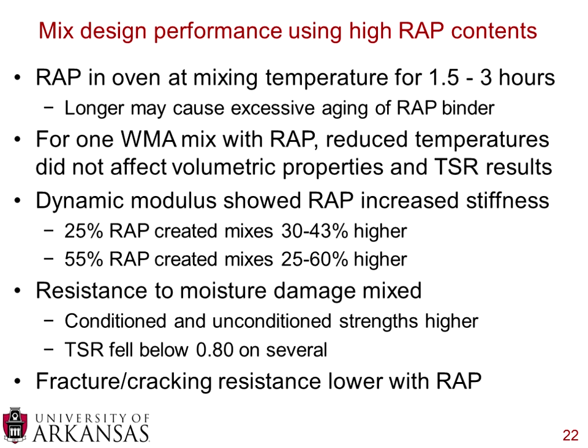They found that one of the tricky things about the moisture damage test, the tensile strength ratio, is that you take your unconditioned sample, which is just a normal asphalt concrete sample that you make in the lab, and you compare that to what's called a conditioned sample, a moisture conditioned sample. For the moisture conditioned sample, what you do is you take your asphalt concrete sample, place it in a bath, place it in a vacuum, and you suck water into that mix to where there's anywhere between, I believe it's 55 and 70% moisture within that mix. Then you run a test on that moisture conditioned sample. So you have both conditioned and unconditioned tensile strengths. The TSR, the tensile strength ratio, is the ratio of the conditioned and unconditioned numbers.